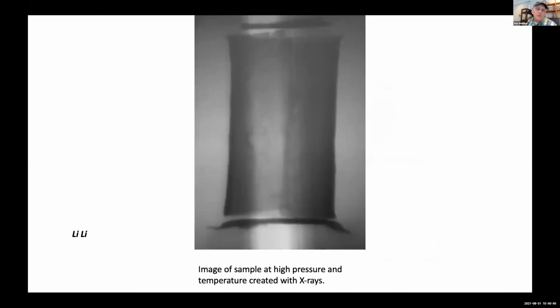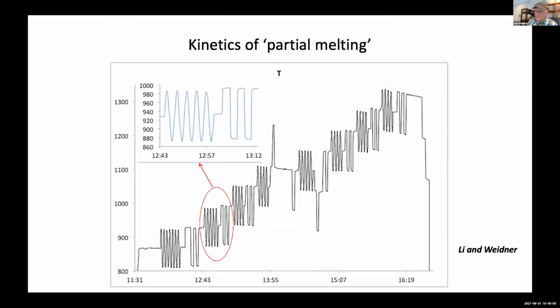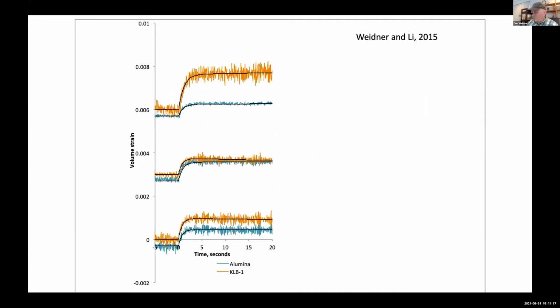If we want to look at volume in the sample, we can take an image, put a rhenium foil in this case around the sample, and put that into the volume picture. This is the way we heated the sample. We wanted it to get used to a certain temperature by going up and down, and then take data from the end. We use a camera. But before we do this last step in temperature, we turn the camera on at 30 frames a second and take images. And from the images, we deduce the volume of the sample,